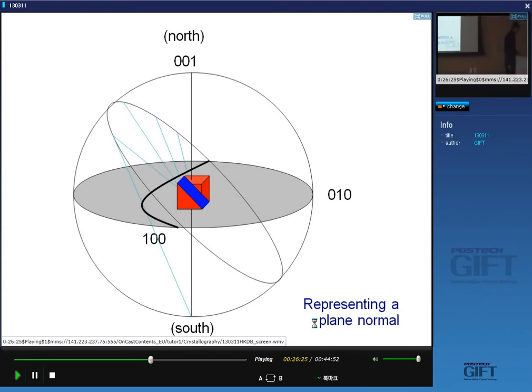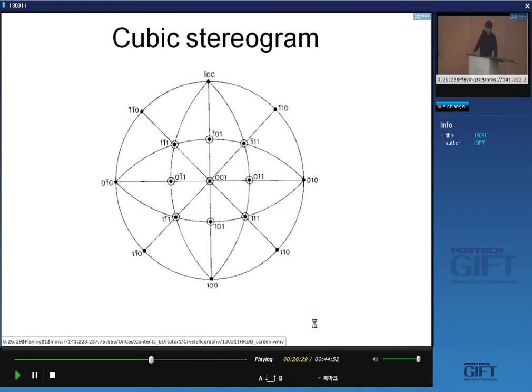So if I go back one slide, this is the normal to the 100 plane, and this of course is the 001 plane. So every point on here must be at 90 degrees to that. Can you see that if I take a dot product of 001 and bar 100, I get nothing? Because when a vector dot product is zero, it means the two vectors are at 90 degrees. If I take a dot product of bar 100 with 001, again, I get nothing. So this is the trace of the 001 plane, and this is the pole, and everything on here is at 90 degrees to this.